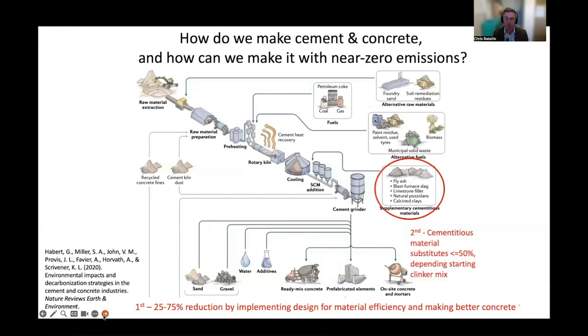Next, we have cementitious material substitutes for the clinker. Most of the emissions come from clinker. We can use fly ash, blast furnace slag, limestone filler, some natural materials. But the key technological advance here is the use of limestone calcined clays, where you use 1/3 ground limestone and 2/3 heated clays together, and they can replace up to half the clinker with virtually no change to the concrete. Just application of this known and approved technology, which meets building code standards across the OECD, would cut the emissions of this sector by 40 to 50%.